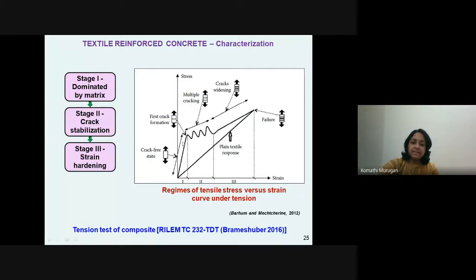What we have here is stage 1, which is dominated by the matrix, and this is the crack-free state. Here, as we start loading the specimen, first the concrete cracks. Before cracking, the concrete takes a certain strain. So this stage is called the crack-free state, or the stage dominated by the matrix. And at the end of this stage, the panel starts showing the first crack in the matrix, that is the concrete. So there is this first crack formation in the matrix.